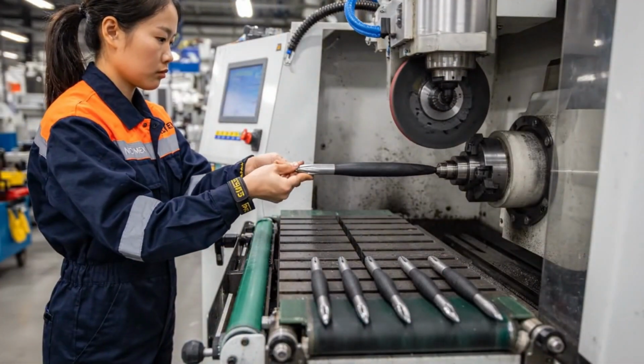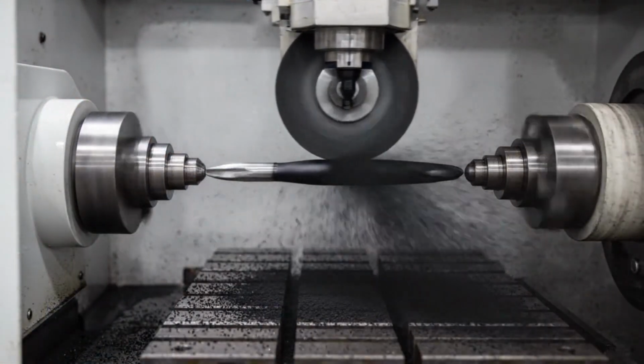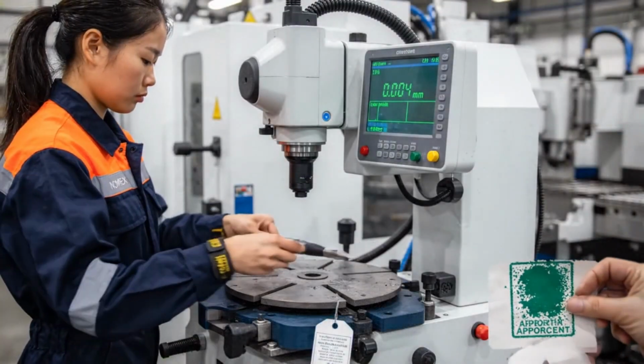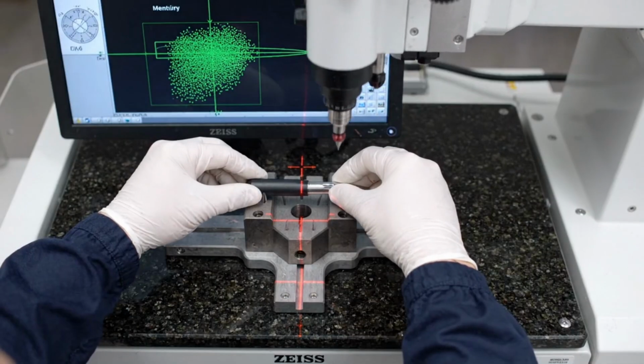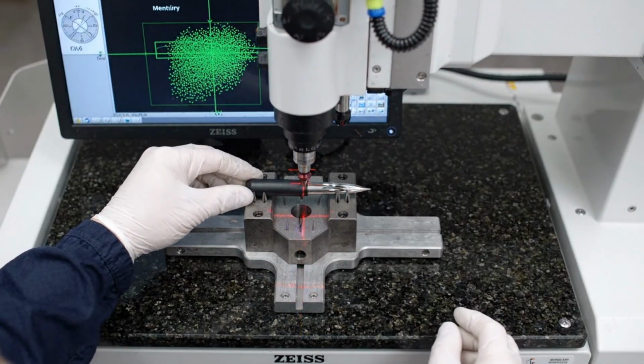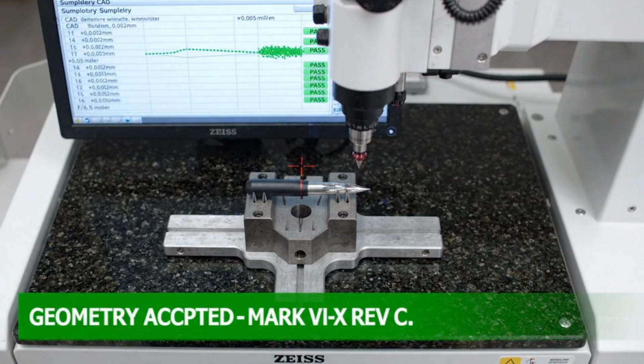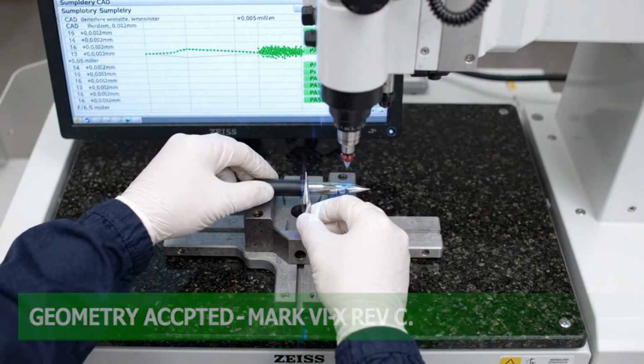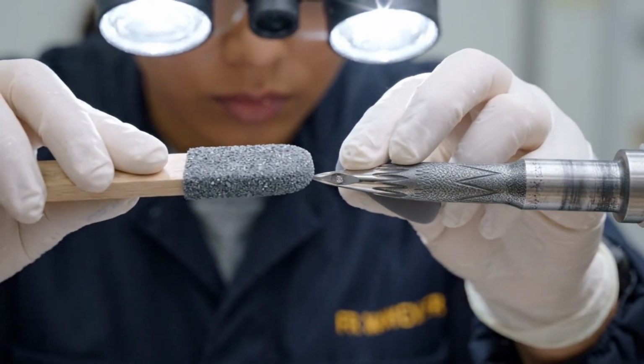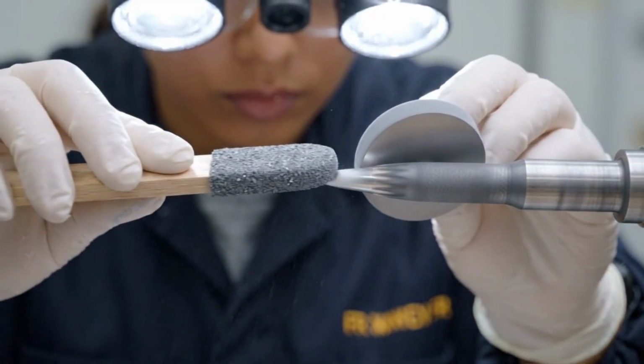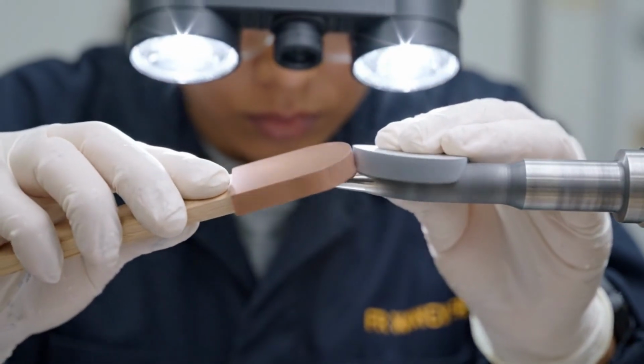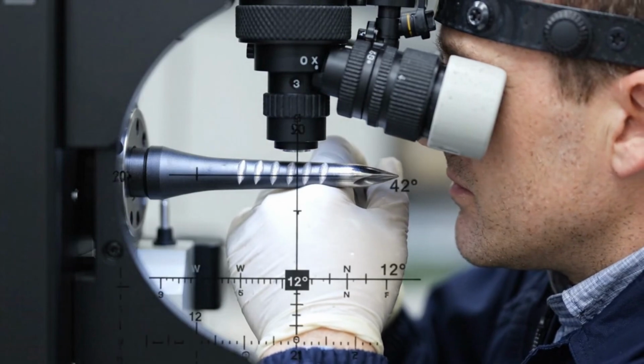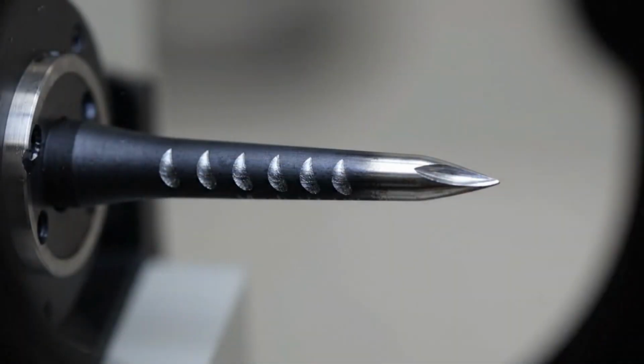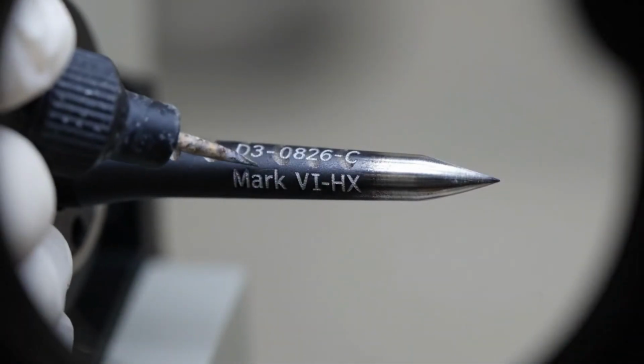The final cylindrical grinding pass removes any straightness deviation greater than 3 microns. The final 0.5 micron diamond polish reduces the tip's surface roughness to less than 10 nanometers. The 40x inspection is the last human judgment the needle will ever receive.